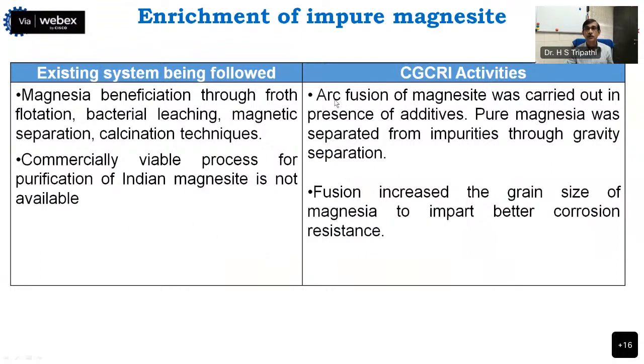At CSIR-CGCRI, we have started some work. Arc fusion of magnesite was carried out in the presence of some additives to purify the magnesia, and by the fusion technique that also increases the grain size, and in this way we can improve the MgO content.